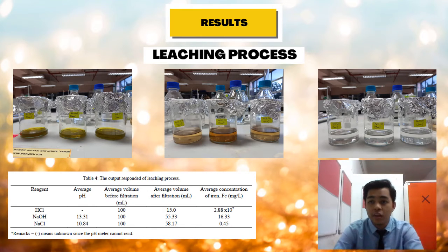As you can see, the figure at the left side shows the greenish color of the metal-rich solution in 5 molar hydrochloric acid. The solution was viscous. It is because the high hydrochloric acid concentration affects the dissolution of EAFS. That's why the iron concentration in 5 molar hydrochloric acid was high.